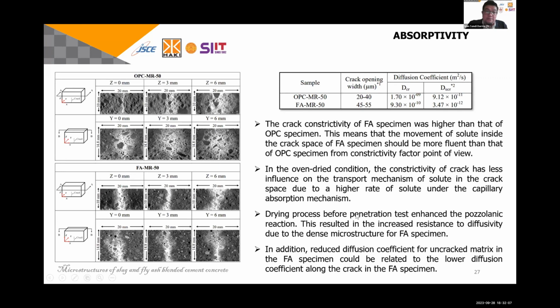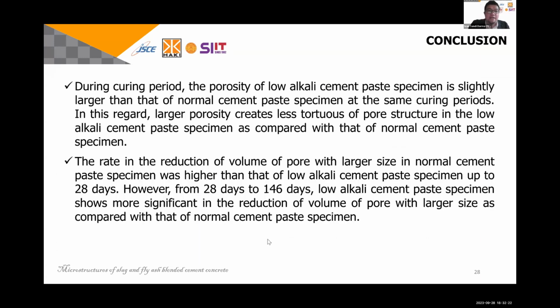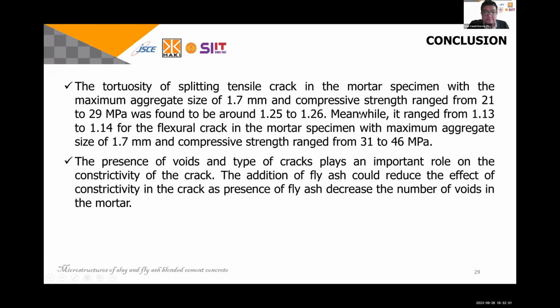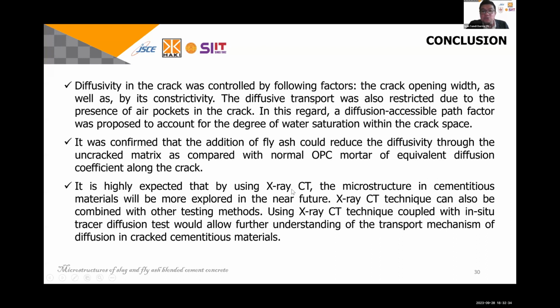In addition, the drying process before the penetration test enhances the pozzolanic reaction, resulting in an increased resistance to diffusivity due to the dense microstructure of the fly ash specimen. And then, as a conclusion, I might skip this one, but the most important thing here is that it is highly expected that by using X-ray CT, the microstructure in cementitious material will be more explored in the near future. X-ray CT again can be combined with another testing. You can combine it with diffusivity, permeability.